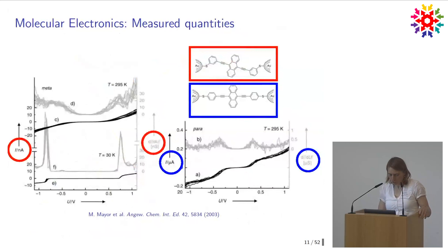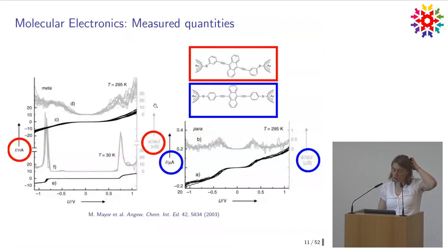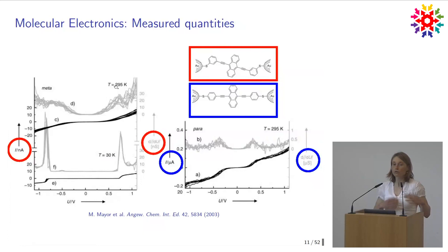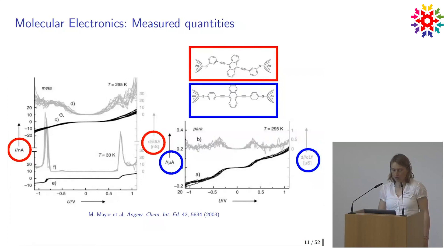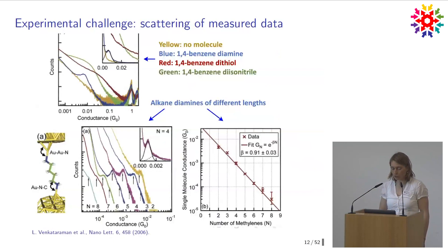That can actually be seen in experiments. We're looking at current-versus-voltage data and its derivative. One important observation is that the data scatter a lot at room temperature. It's surprising enough that destructive quantum interference survives these fluctuations at room temperature. The data fluctuate quite a bit when you repeat measurements at room temperature, which is a general problem both for applications and for simulations.